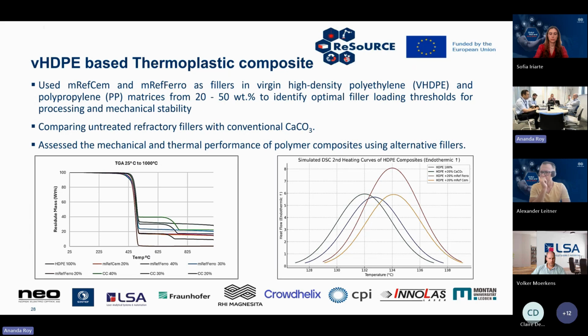So for example, with the TGA, it is quite substantial to see that there's a trend of increasing residue with higher filler content, which is quite observable with all of the fillers that you can see. The MREF-Ferro especially shows a very high inorganic content, so basically it has a much higher thermal stability. On the right-hand side, where you can see the DSC, or the thermal behavior of these materials within the high-density polyethylene thermoplastic, you can see there's quite an increase in both melting and crystallization temperature, especially for the MREF-Ferro material, indicating that the MREF-Ferro is a promising candidate for applications requiring high stiffness, dimensional stability, or thermal resistance as well. But with the inclusion of calcium carbonate and mRefCem, minimal influence can be observed within the thermal transition.